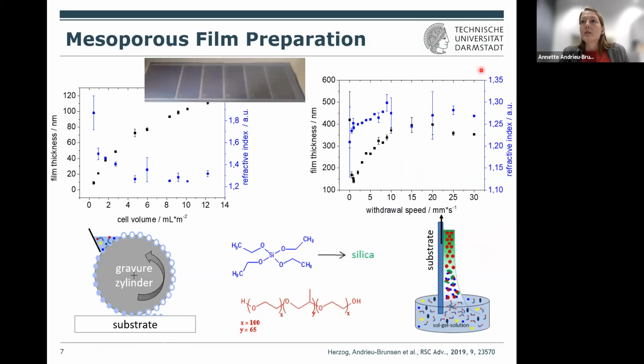So we prepare these materials using either dip coating, a quite common procedure in this nanopore sol-gel chemistry community, or what we developed as well is gravure printing. What you do in gravure printing is that you have a solution and a cylinder that goes through the solution and then deposits the solution on the substrate. And the advantage of this over dip coating, which is demonstrated here, where you basically immerse a substrate into a solution and pull it out, is that the deposition is quite homogeneous. You can well control the thickness of these films, and it is advantageous if you want to deposit multilayer films, because the contact time of the first layer with the solution for the second layer is not that long.